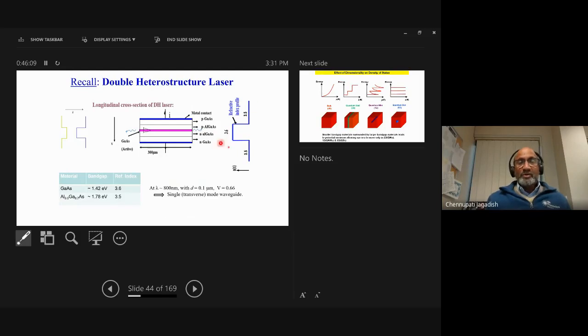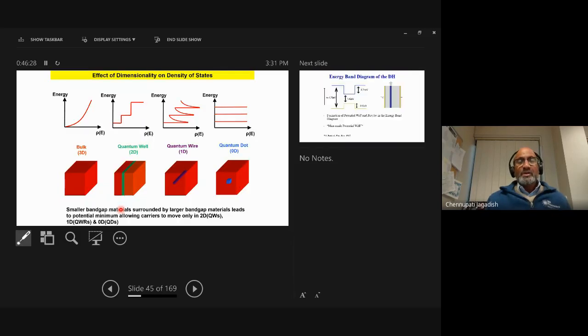So again, we talked about the double heterostructure lasers, and just to give an idea, you have a double heterostructure with a larger band gap material and a smaller band gap material sandwiched here. Gallium arsenide is typically used in this case, and aluminum gallium arsenide has a larger band gap. So what will happen if you reduce the thickness of the smaller band gap material? That's where we started moving from bulk materials to quantum wells, quantum wires, and quantum dots.